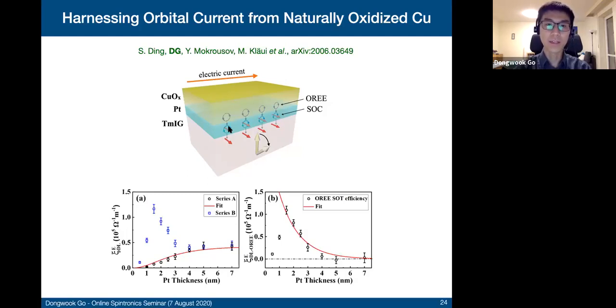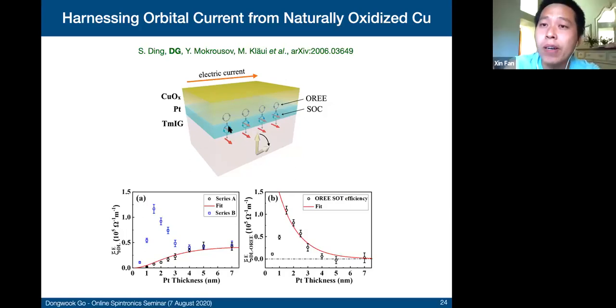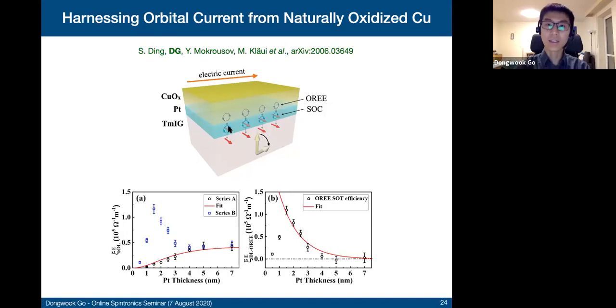But if we go to light elements with small spin-orbit interaction, this is governed by the crystal field in the system, and I cannot say it in simple words, but just from my experience with many different simulations, it seems to decay in about 3 to 5 atomic layers. So it's just a 1 or 2 nanometer scale. It's pretty short, because the energy scale at which orbital interacts with the lattice is pretty large. Therefore, decay is very fast. It's an intrinsic decay, not due to any defects in the system.